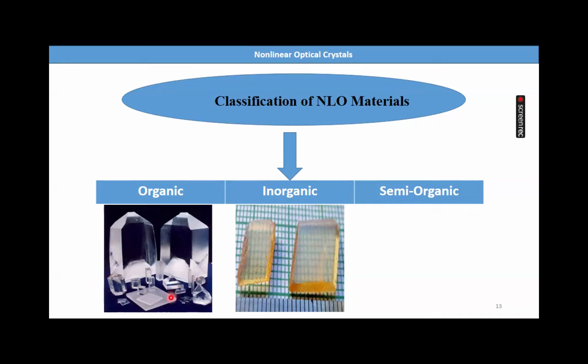Even so, the majority of organic compounds, 70%, fail to show second harmonic generation activity because they crystallize in a centrosymmetric space group with inversion symmetry. Given this circumstance, a number of methods for producing acentric crystals capable of showing SHG have been suggested, such as, the first one, chirality, electric poling, hydrogen bonding, channel inclusion alignment, dipole-to-dipole interaction, lambda-type molecules, and co-crystallization.